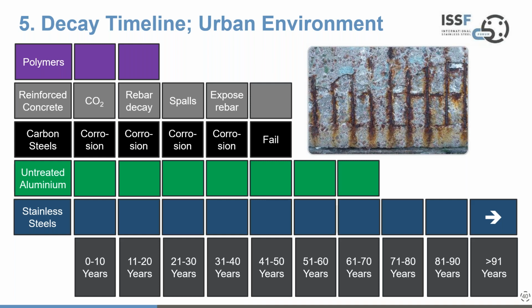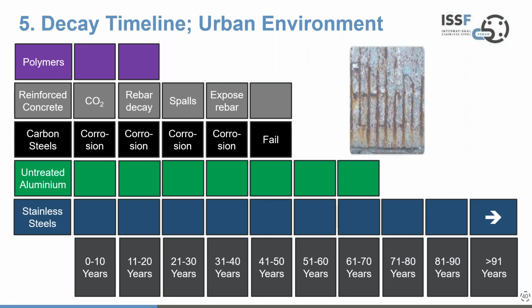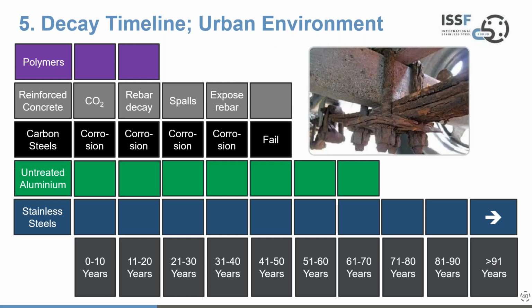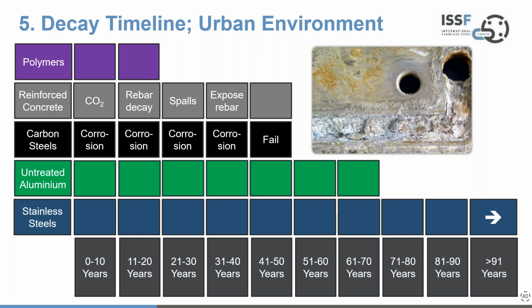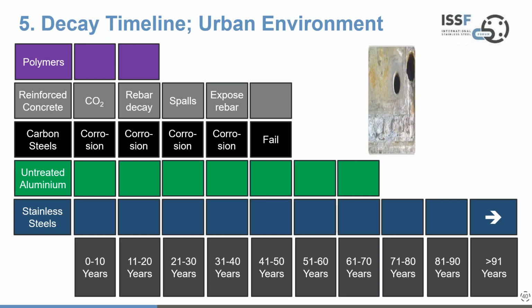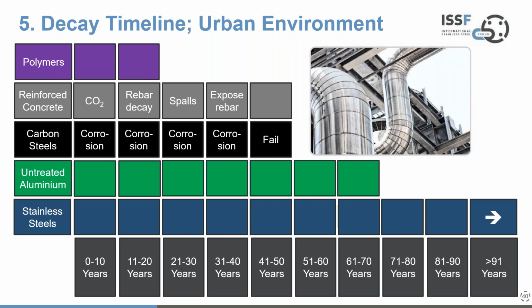Carbon steels start to corrode pretty quickly from day one. They rust fairly uniformly, and they will fail over a similar sort of time scale. With untreated aluminium, bear in mind there are different treatments for these materials, you will start to see these corroding progressively over time, but you've got a better life, in excess of 60 years typically. And then stainless steels at the bottom of this will give you at least 100 years of good life and look pretty pristine, but recognize there is still the need to prevent things like pitting corrosion by regular cleaning and good design of these products.